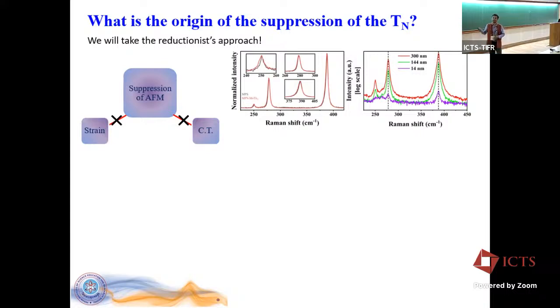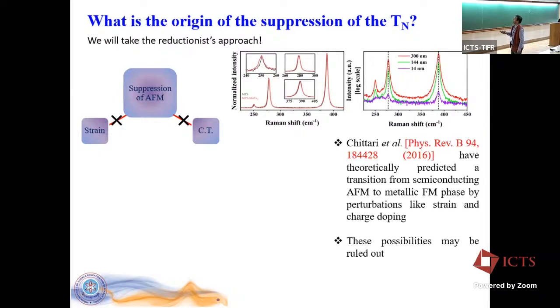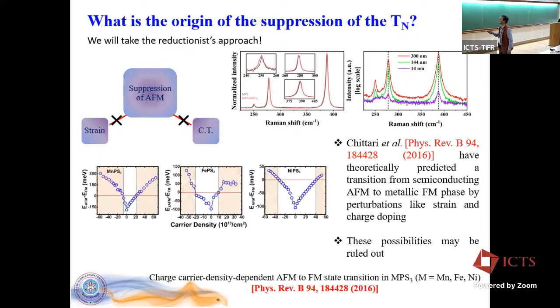From this set of data, we can confidently rule out strain, at least not at the level where we can perceive it. Then about charge transfer, this is the calculation by Chittari, and they showed that if we have sufficiently high charge doping, on the order of about 10^14 per cm², then it can actually switch from AFM to FM, ferromagnetic ordering.